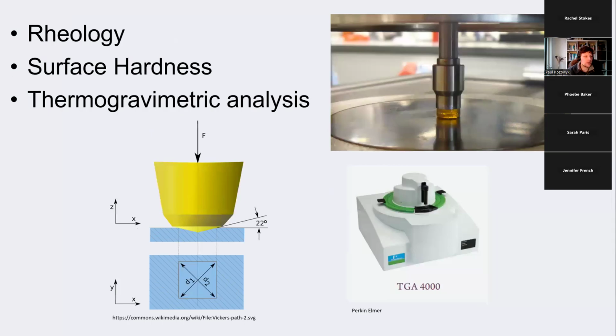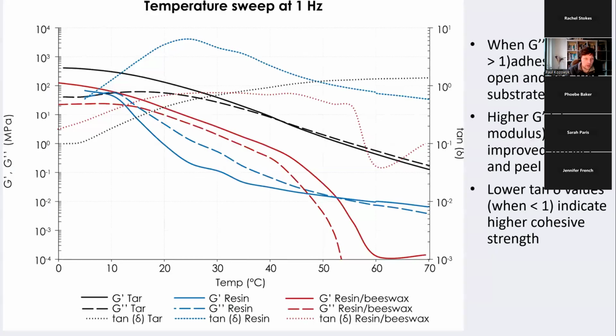So then to test these criteria, I looked at rheology to measure the flow of the adhesive over a range of temperatures, surface hardness of the material before and after heating to different amounts to show how the hardness, its ability to resist deformation, changed as a function of time, and also its thermal degradation while being heated in thermogravimetric analysis. I'll quickly skim through these results, but this one, it looks like a mess, but I'll give you a quick rundown with a few key areas highlighted.